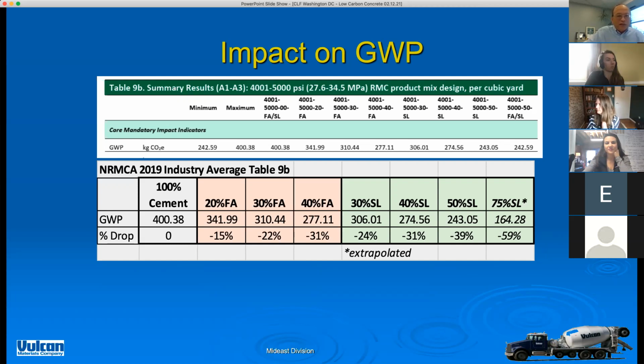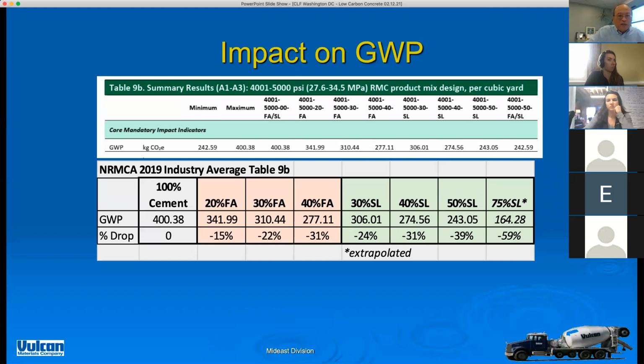Again, Eric has referenced this as well: the GWP reduction from adding different amounts of fly ash or slag. One thing that's not shown on the slag side is that we can actually go up to 75%. Using 100% cement as a reference, look at the percentage reduction in GWP, close to 60% reduction using as much as 75% slag cement in the concrete. So next slide, please.